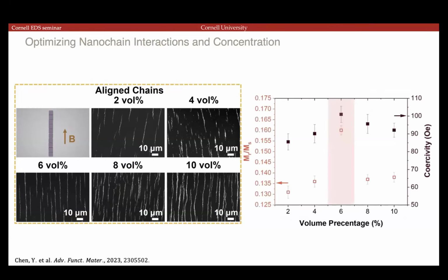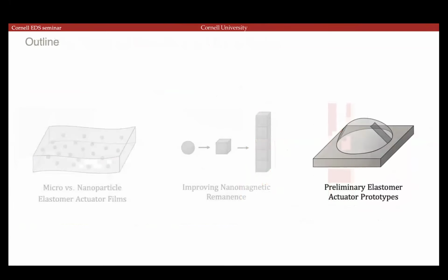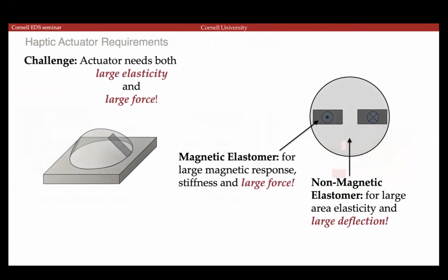So if you vary the amount of magnetic material, you actually get a sweet spot of remnant magnetization of the composite at a 6% volume concentration. That also corresponds to the largest coercivity within the film. And both of these correspond to what we theoretically calculate as the ideal composition. So without further ado, let me show you some fun videos of what the students did.